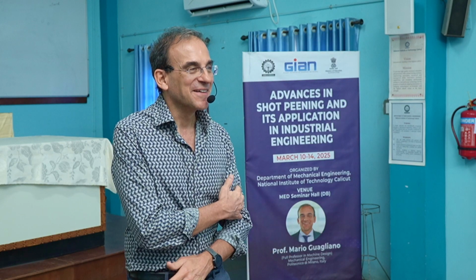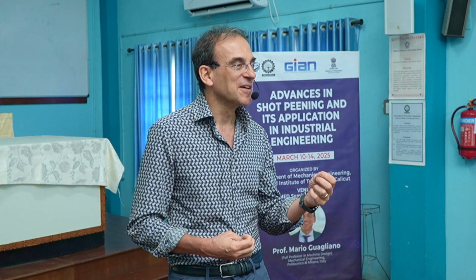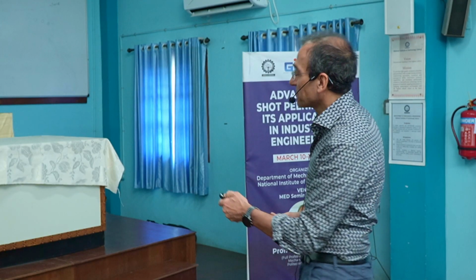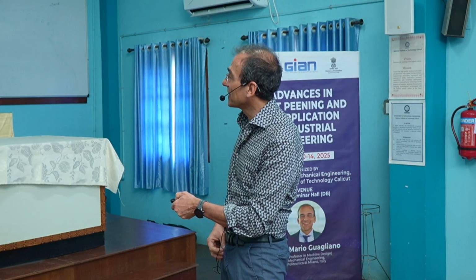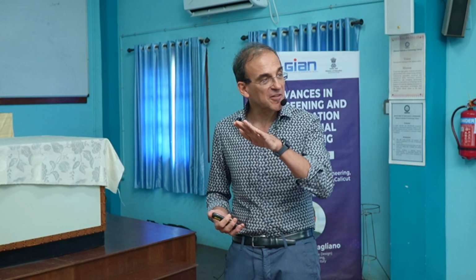Yes, but higher roughness also means less fatigue life, no, sir? How do we compromise these two conflicting aspects? Indeed, we must find a trade-off. We must find something that makes possible a better bone integration, integration into the human body, that at the same time does not cause a strong decrease in the fatigue strength. But it's important to notice also that if we perform severe shot peening and grind the surface, so we smoothen the surface, the water contact angle remains almost the same. So in this case, we are also improving fatigue.